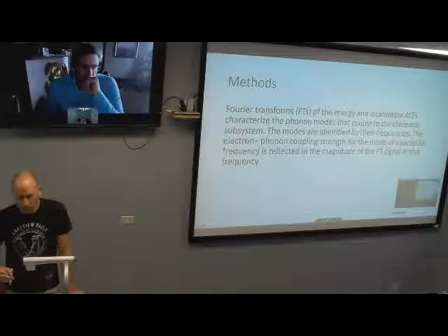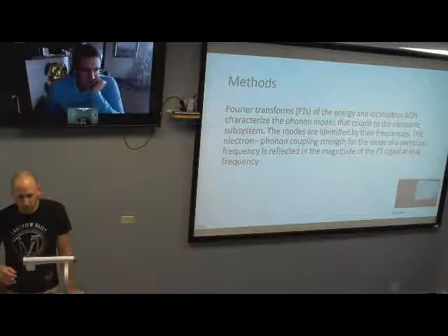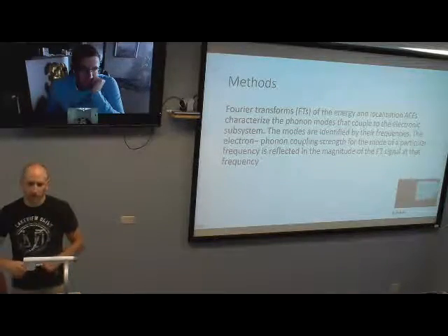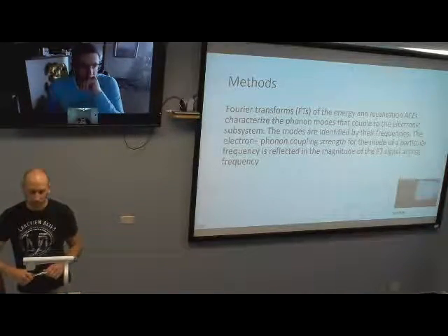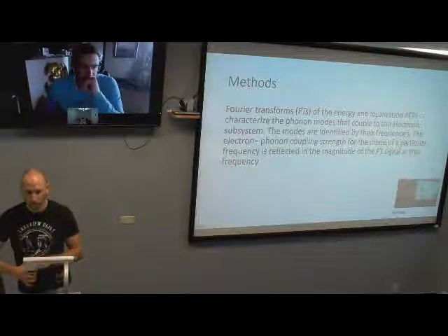They do it as it is supposed to be done, through DFT and the regular classical force approach to nuclear motion. Technically, it can be anharmonic. There is no approximation saying that your system at 300 Kelvin really behaves harmonically. So first, they do not really find normal modes. They find actual frequencies of this motion, which correspond to this temperature.